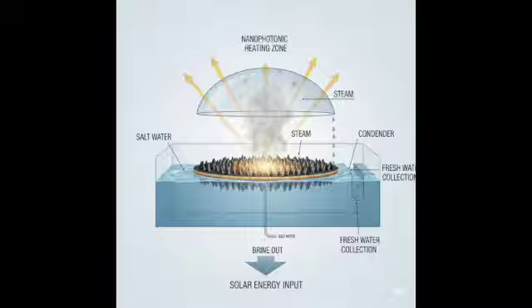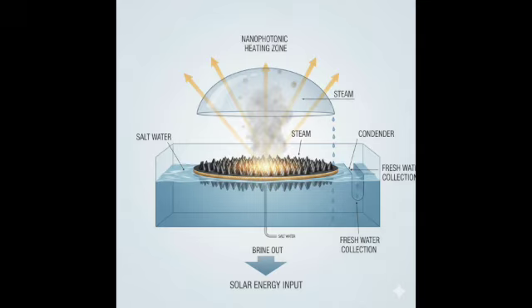What about the photothermal layer itself? Thickness. It's another balancing act. A thicker layer might absorb more light overall, but if it gets too thick, it can start blocking the membrane pores underneath or increase the thermal resistance within the layer itself, impeding vapor flux. Right. So the ideal is usually a very thin but highly absorbing layer that maximizes light capture without hindering mass transport. The concentration of the photothermal material within that layer is also critical.